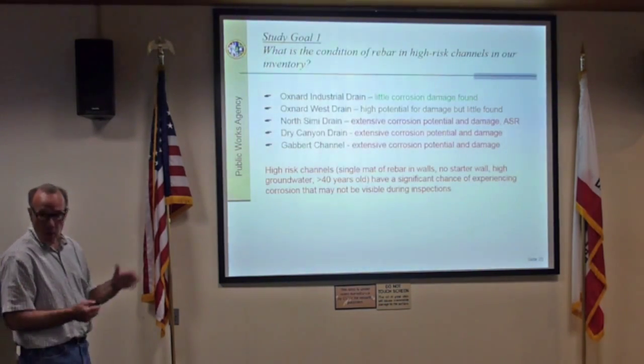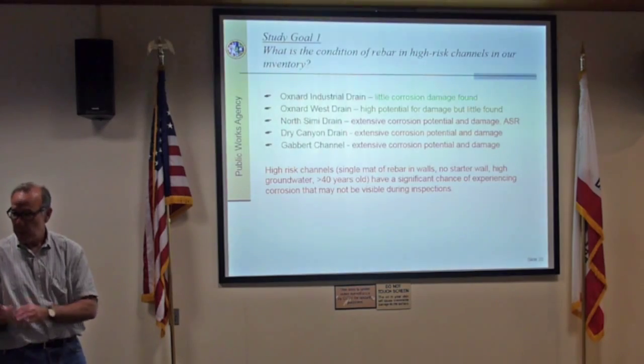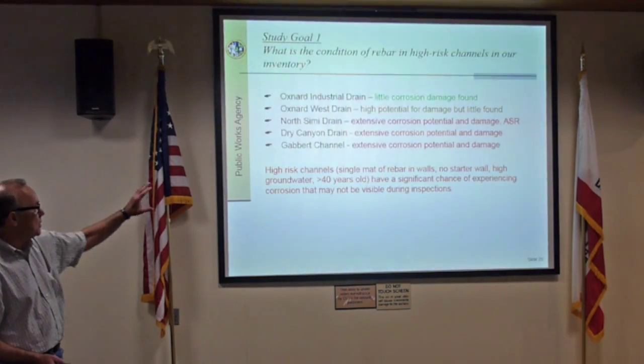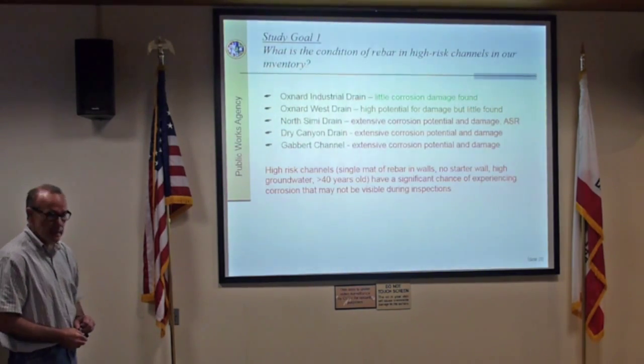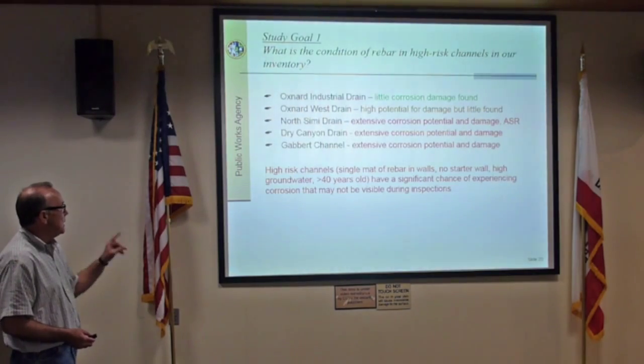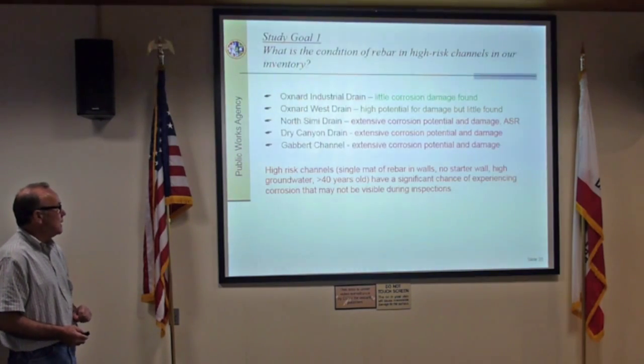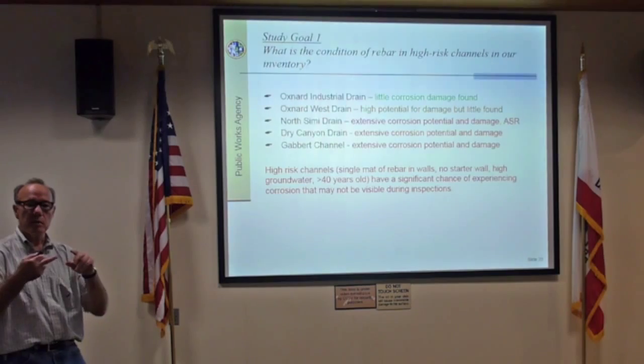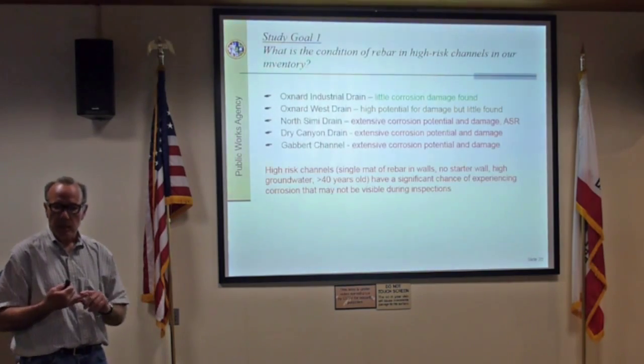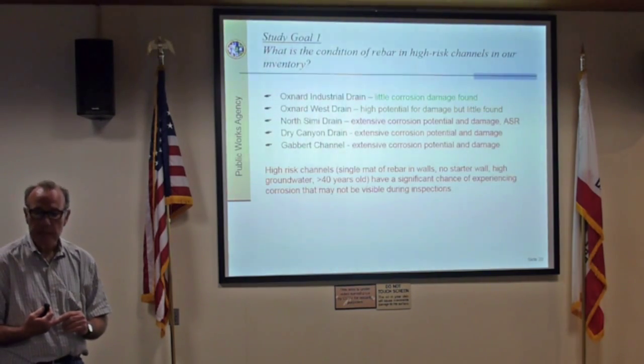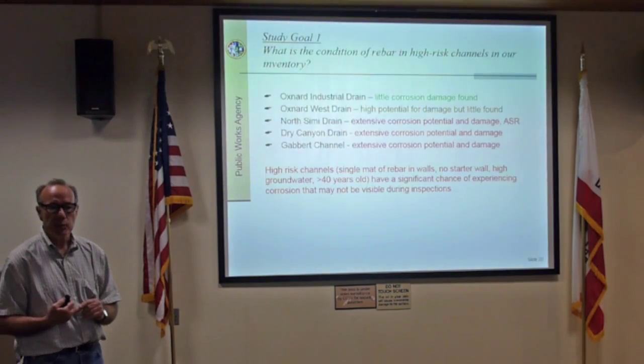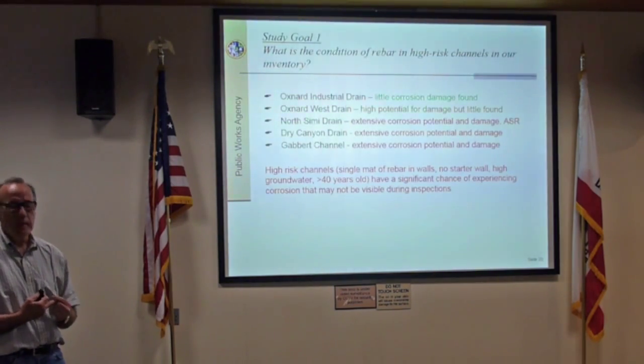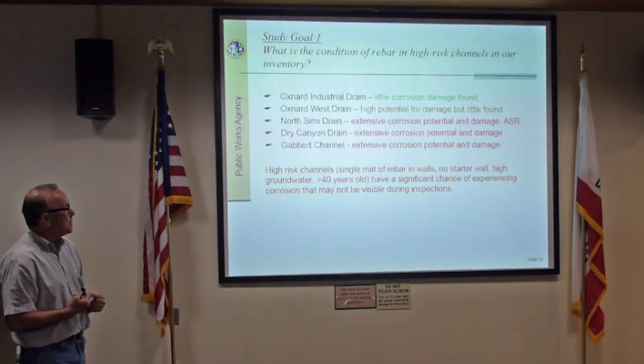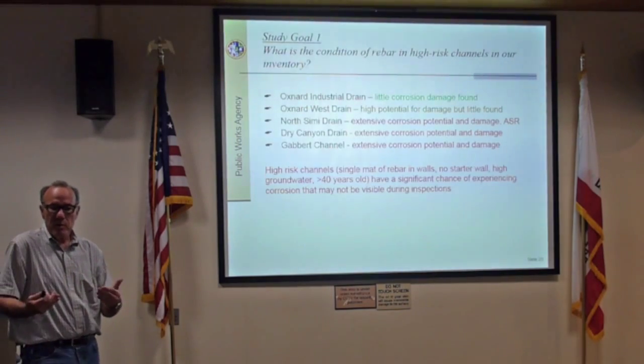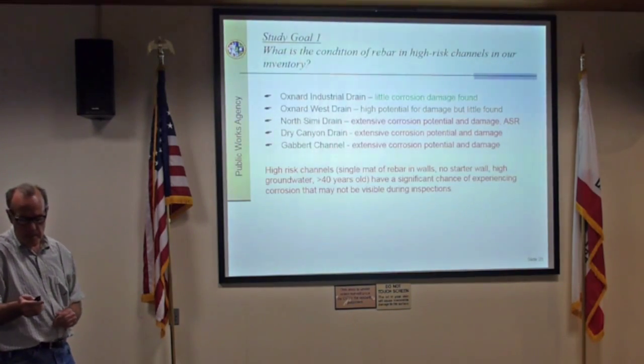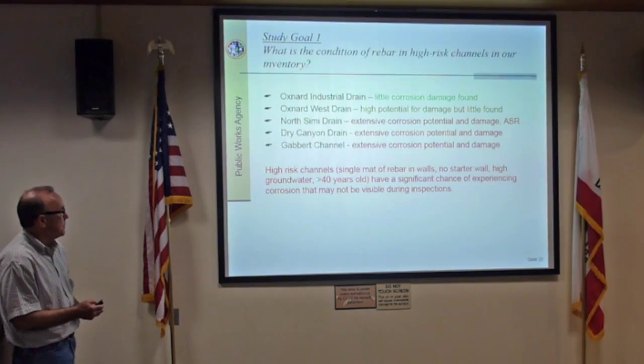So overall, in these channels that we looked at, there's little corrosion damage that was found in the industrial drain section. Oxnard West had high potential for damage. All these corrosion rates, the chloride tests, and resistivity tests that we measured say it's at high risk, but we didn't really find much. So it's not a great conclusion in that regard. We know it's at risk, but we didn't find a lot of corrosion manifesting itself in those particular areas.